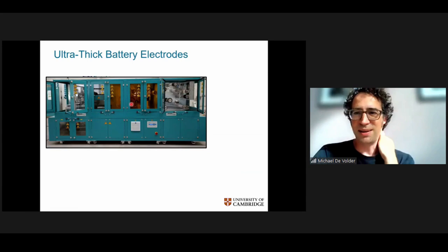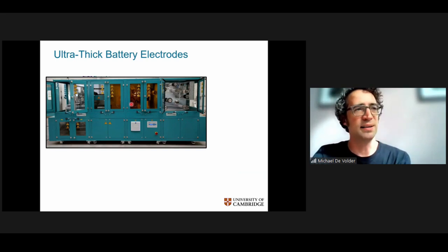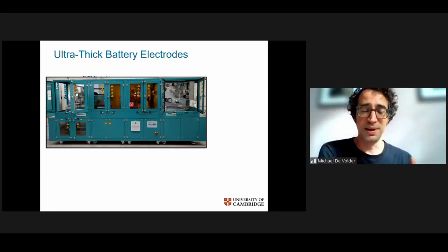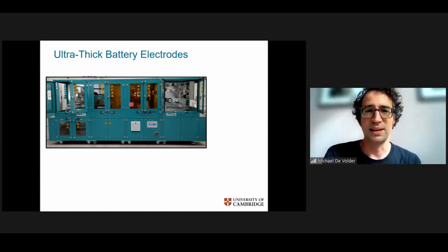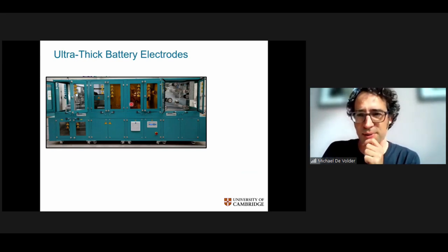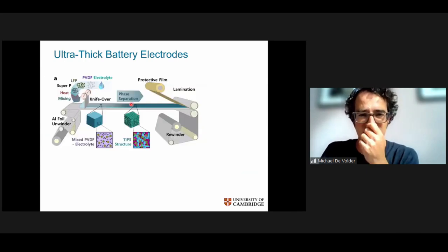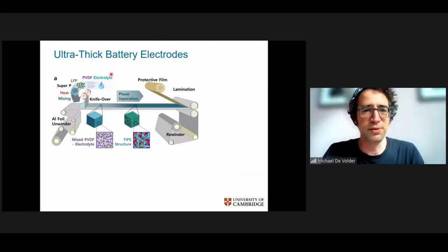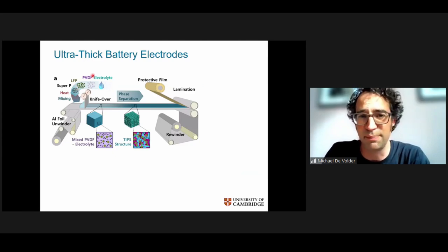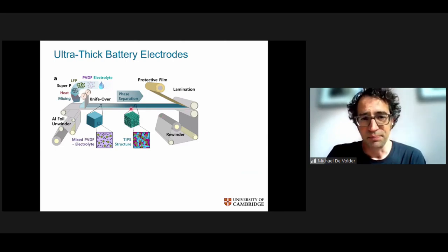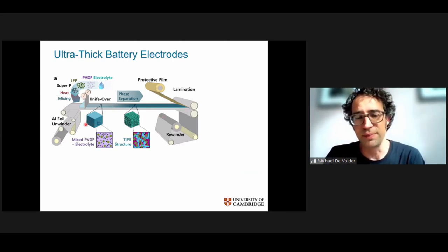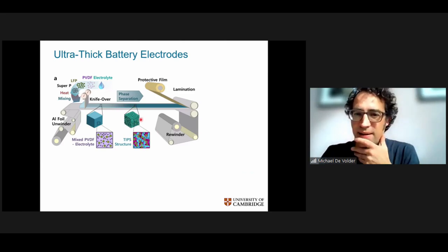Great, so what I mentioned in the beginning of this talk is that it's really imperative to find manufacturing processes that are compatible with how people in industry are making their battery electrodes. And so to do that, we've demonstrated a process on the roll-to-roll process I just discussed. And so how that works is as follows. We take our mixture of active materials and PVDF and solvents, which I just discussed. We heat that up to 150 degrees, and then we cast that onto our continuous coating process. Initially everything is mixed uniformly, but then as it cools down in the process, the phase segregation will take place, and we form this nice bicontinuous network that allows for thick electrodes to operate nicely.